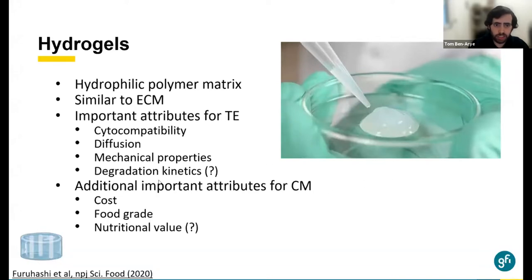We don't want a gel that degrades after 5 minutes, and we don't want it to remain over 1 year. So we want something in the middle, a few weeks of degradation, and perhaps also adding some break points that allow the cells to break down the hydrogel using some of the enzymes that they produce, the metalloproteinases. Some important attributes for cultivated meat in terms of hydrogels are the cost of the hydrogel, being food grade, and also providing nutritional value in case they are maintained as part of the scaffold.